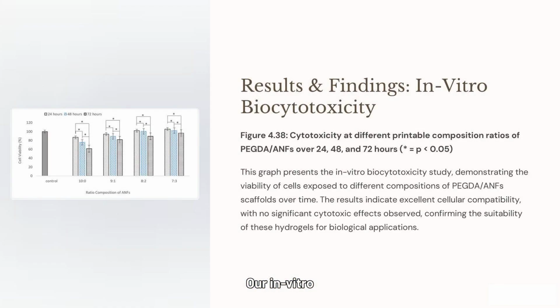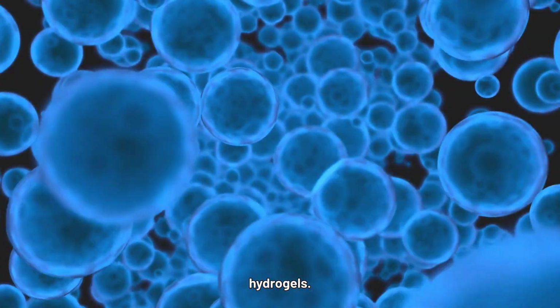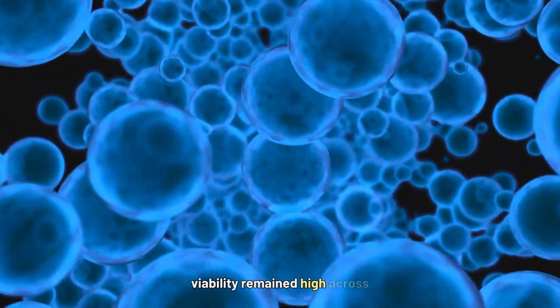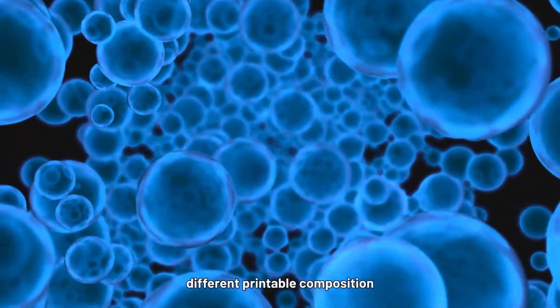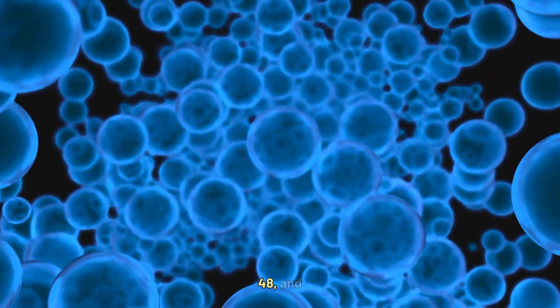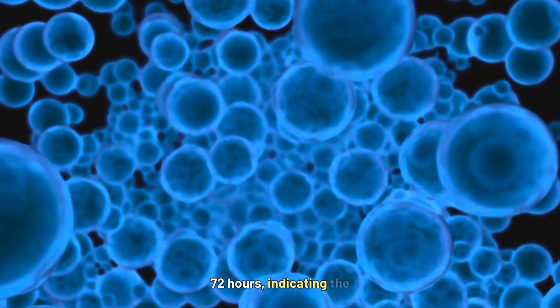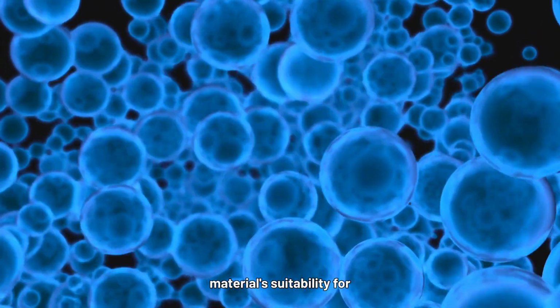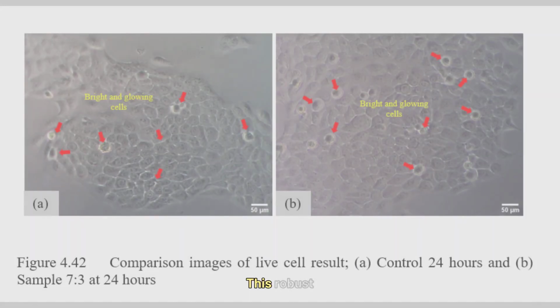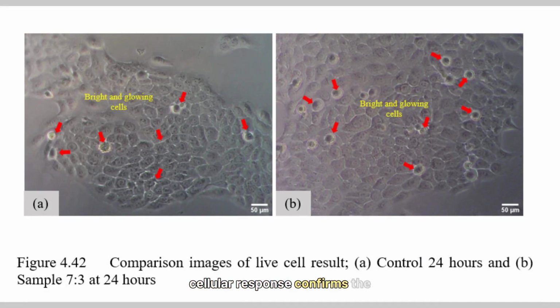Our in vitro biocytotoxicity study demonstrated excellent cellular compatibility of the PEGDA/ANFs hydrogels. Cell viability remained high across different printable composition ratios over 24, 48, and 72 hours, indicating the material's suitability for biological applications. This robust cellular response confirms the non-toxic nature of our developed biomaterial, a critical requirement for tissue engineering.